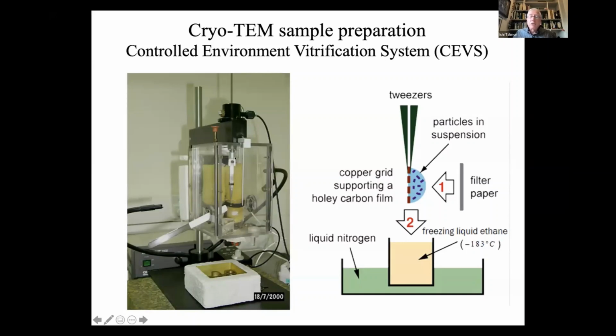So basically, the procedure is very, very simple. We have an electron microscope grid with a perforated carbon film that you already saw in the lung surfactant specimen. It is held here. This is the schematic, this is the picture here. This is the grid, by the way. You apply a very small drop of your liquid, about 4 microliters. Then you blot most of it in order to form a very thin film. I'll show you in a minute. And then you drop it into freezing liquid ethane, which is cooled by liquid nitrogen.